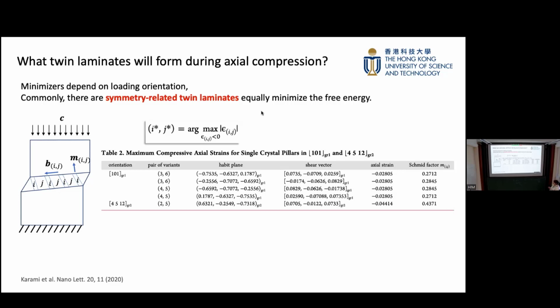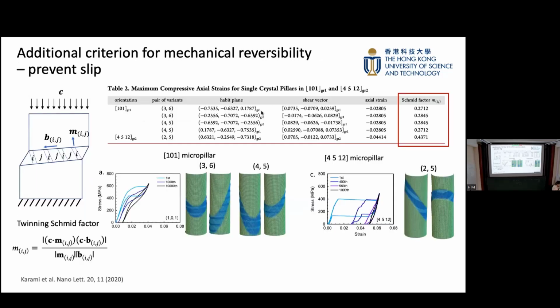Okay. Go ahead. And we also show in another orientation the minimizer obviously changes because the loading direction changes, and that corresponds to a bigger axial strain. What we did is we fabricated micropillars along the 101 orientation and the 4512 orientation and loaded them. We find the first cycle transformation axial compressive strain exactly matches this value, and for this one, it exactly matches this value for the first cycle.